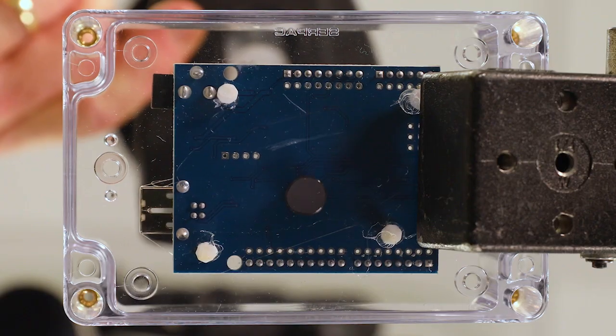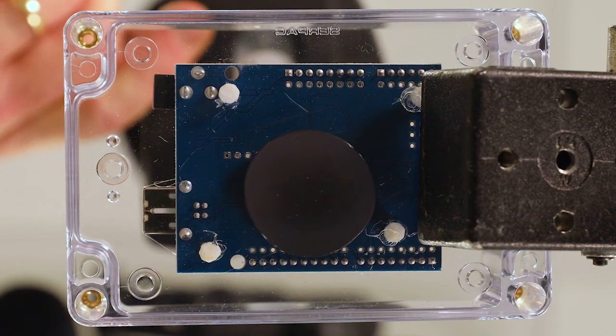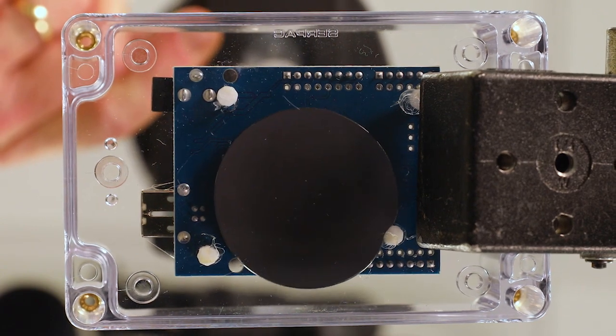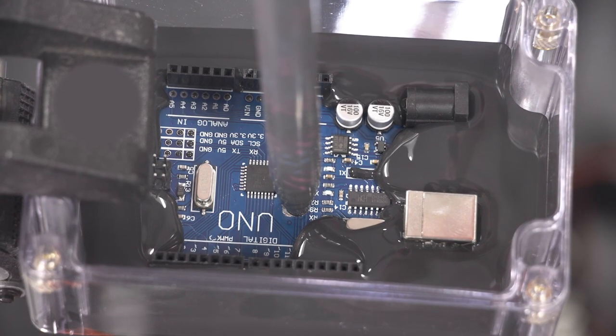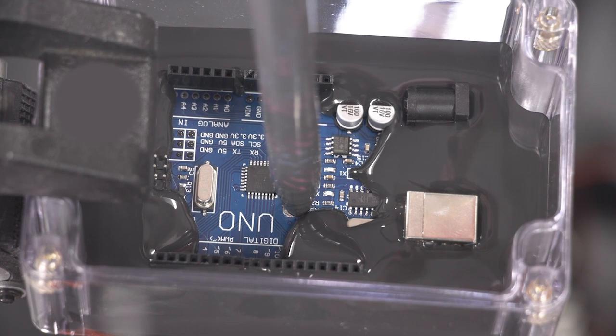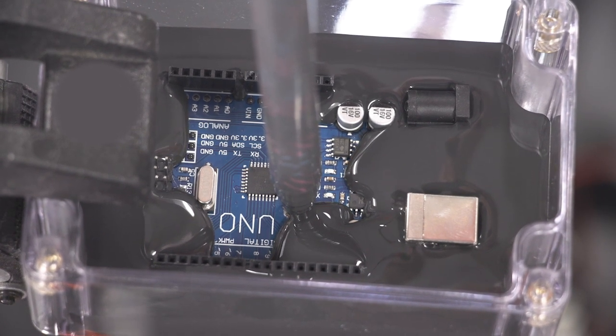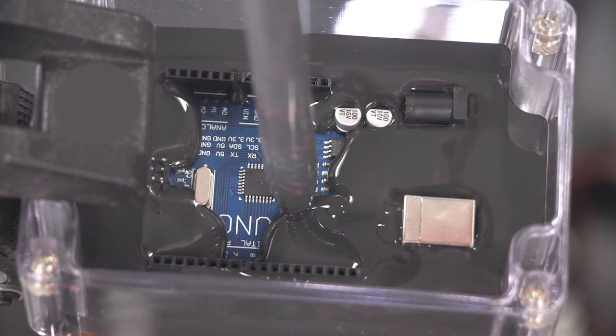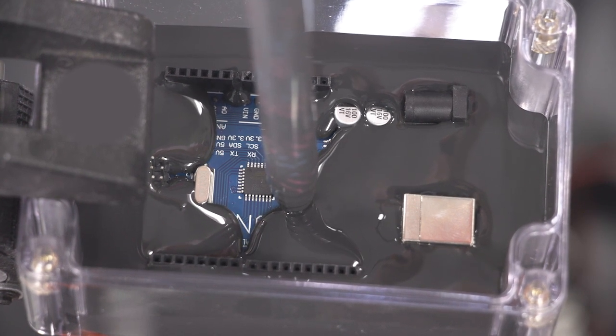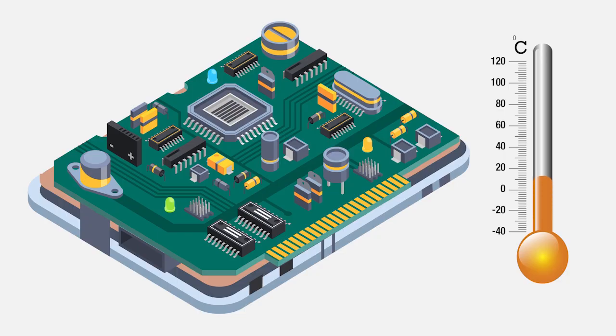Potting compounds based on epoxy and polyurethane chemistry are used to encapsulate and protect delicate electronic parts from moisture, vibration, and mechanical stress. However, the repeated thermal cycling experienced by power electronics can introduce challenges. As the temperature changes, materials can expand and contract, potentially leading to mechanical stress on the components within the power electronics. Over time, this stress could cause cracking or delamination, exposing the power electronics to environmental factors.